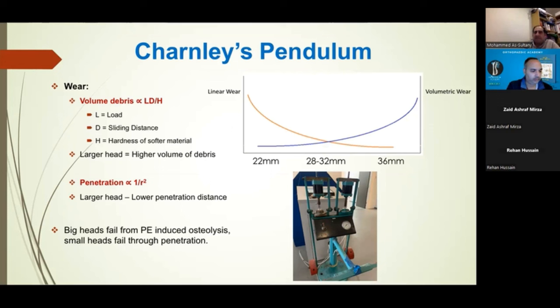So you can see here on the graph that femoral head size is quite key. And you've got two types of wear: linear wear and volumetric wear. Linear wear is the amount of penetration through a material, and volumetric wear is dependent on the surface area, the amount of surface area where that happens. So with a larger head, obviously you get more volumetric wear, and with a smaller head you